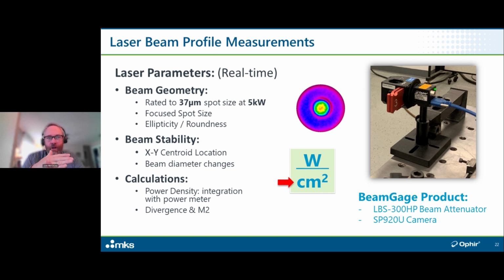Since it is looking at the beam on an XY plane, it will tell you if the beam is traveling around so that you can ensure that it remains consistent with the location of your weld. And because it is dumping about 99.99% of the beam, you can put a power meter underneath and collect it, use it as a beam dump, or you can collect the absolute power and calculate power density. These devices also let you calculate a divergence angle and M² if you move it through the waist. Again, we're talking about power density, and verifying that the spot size is what it's designed to be, and that it is consistent in its location.